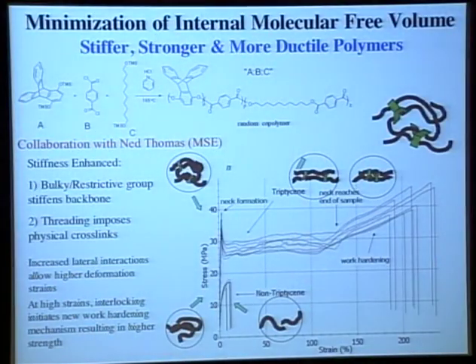Here's what the structure of that same material looks like, and it has a triptycene in it. You can just eliminate the triptycene in this. The triptycene is relatively dilute. The monomers are in different ratios. And here are the actual stress strain curves. And one of the things that's really nice about this, with Ned, is we can get a material that's more ductile, that is, it stretches longer, and has higher strength. We've been able, again, to get a series of mechanical material properties that aren't necessarily always commensurate with each other.